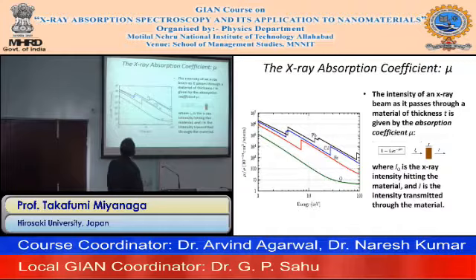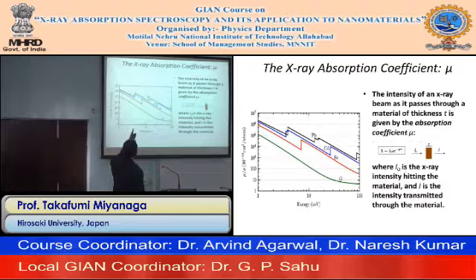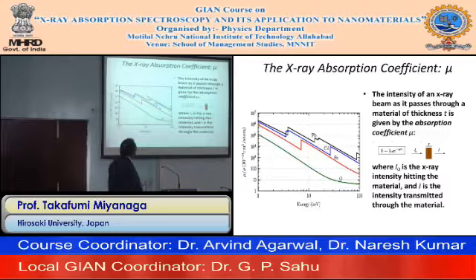Here we have plotted the mass absorption coefficient versus the energy of the X-ray wavelength. The curve is not linear, but has certain discontinuities after certain gaps. Those discontinuities where the curve goes straight then comes down — these are the absorption edges. As I was telling about the mu value: I = I₀ · e^(−μt).